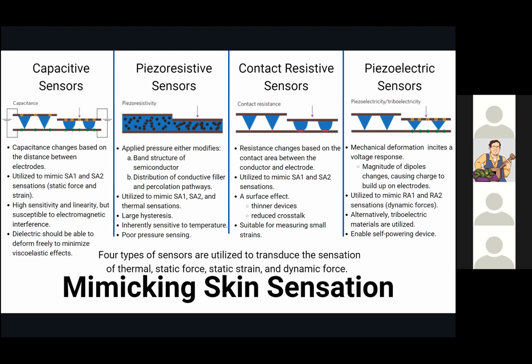Therefore, if you'd like to use resistive sensors that are purely for force transduction applications, then we'll usually stick to contact resistive sensors. So essentially, resistive sensors, both of them, function through 2 mechanisms based on the principle that resistance is equal to resistivity multiplied by length over cross-sectional area. The first mechanism utilized by piezo-resistive units is due to a change in resistivity caused by the deformation of semiconductor band structures and percolation pathways between conductive particles. And the percolation pathways are just the conductive pathways.